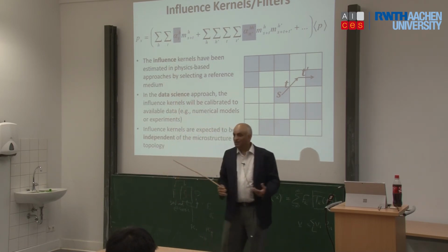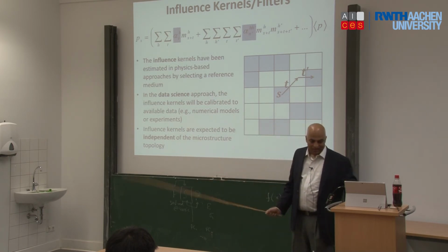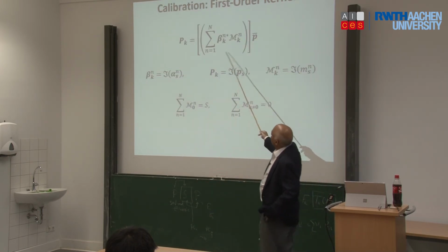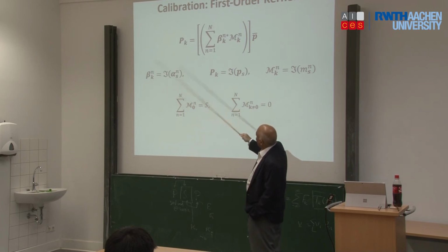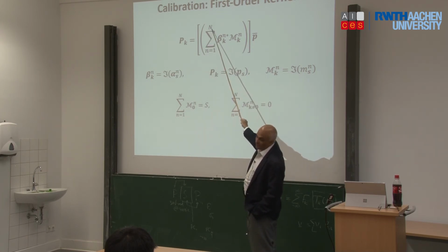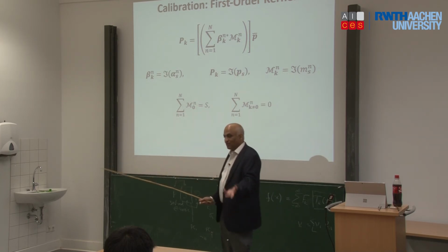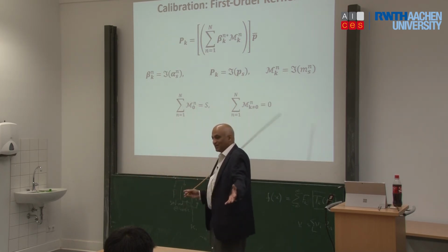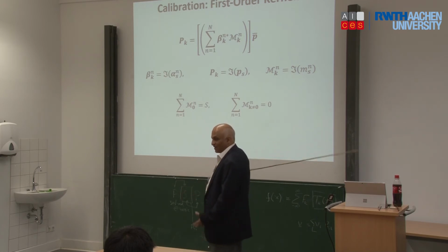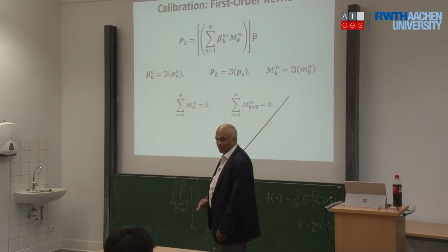So, regressing over a million variables is very complicated. Whereas, if you do FFT, then that summation sign on the T goes away because of the convolution, it completely goes away. So, in the frequency space, the summation is only on the number of states. So, if I have only 2 states, this has only 2 unknowns, just that I have to do all the frequencies. So, in one way, I have millions that are coupled. Here, I only have 2 or 3 things that are coupled.